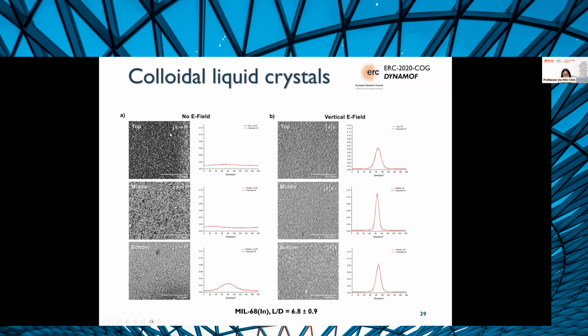The reason for this in this case is that even though its aspect ratio is theoretically much higher than the requisite 4.7, you also have a very fast sedimentation. And what happens then is that when you have rapid sedimentation, the particles get arrested in these jammed states where they are not in their thermodynamically most favored situation, with this perfect packing order.